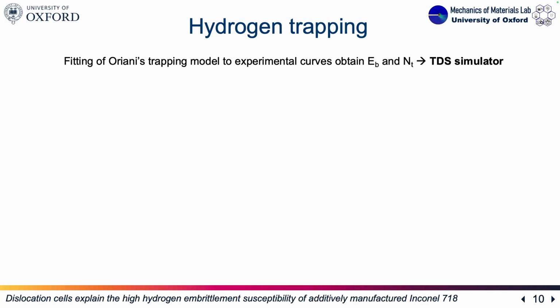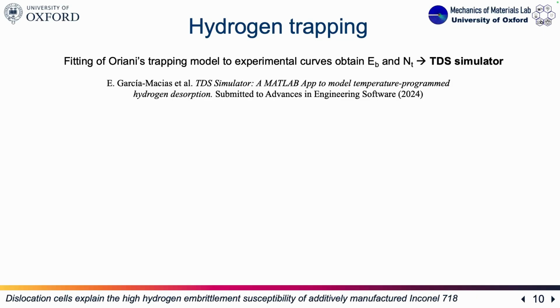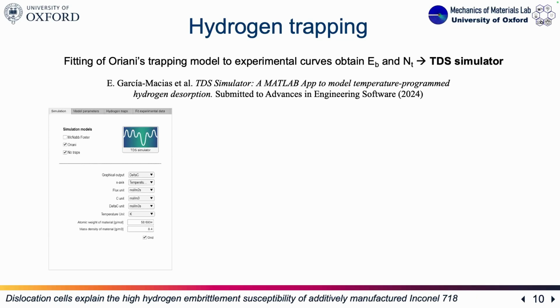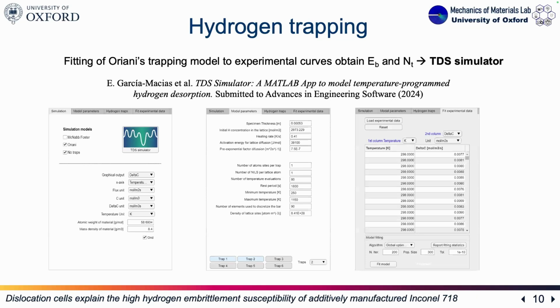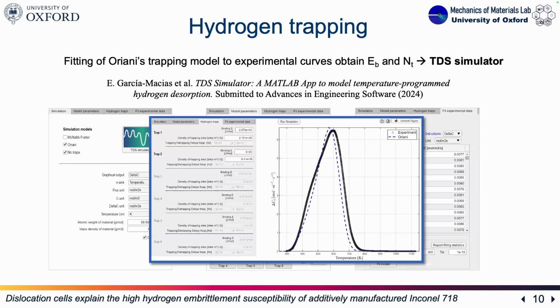Then we wanted to perform a hydrogen trapping analysis using Oriani's theoretical framework. So we have to determine the trapping binding energy and the trap density. That's why we use the TDS simulator. That's just a MATLAB app that our group has developed recently, where you can put the details of your experiments, like your experimental conditions, the details of your sample, your thickness, and so on. And you can do a fitting of the experimental curve, and it can provide both the binding energy and the trapping density of hydrogen in your material.